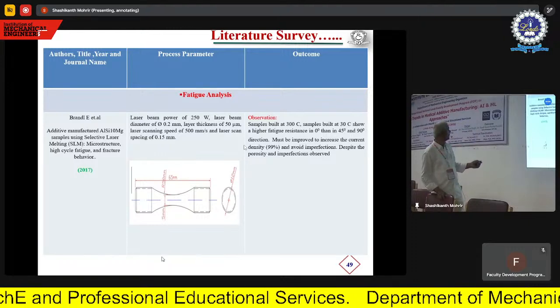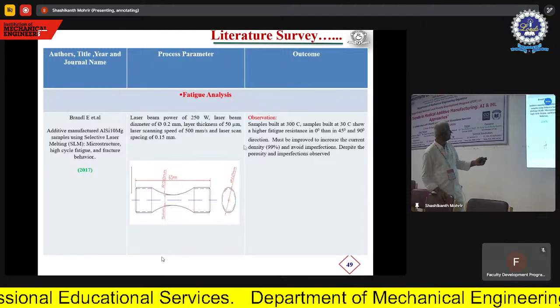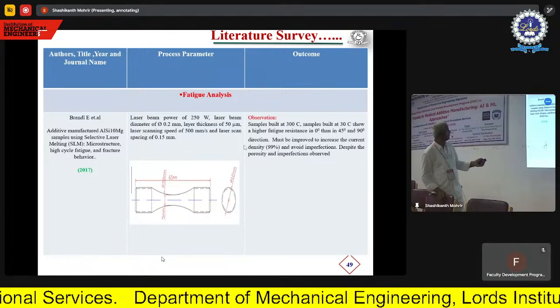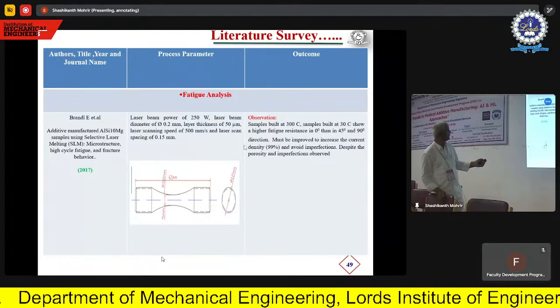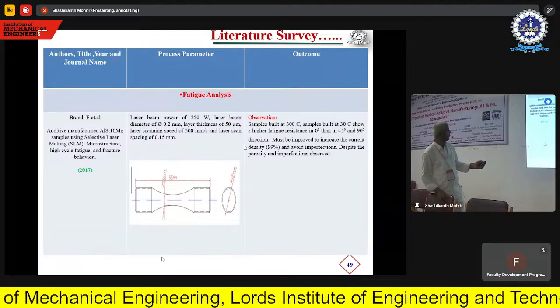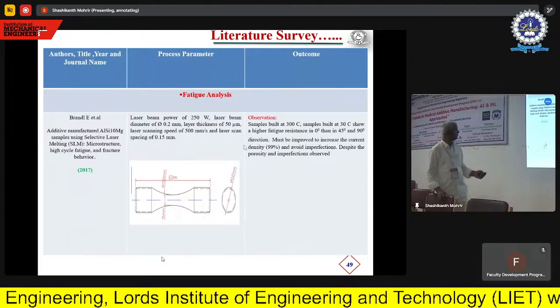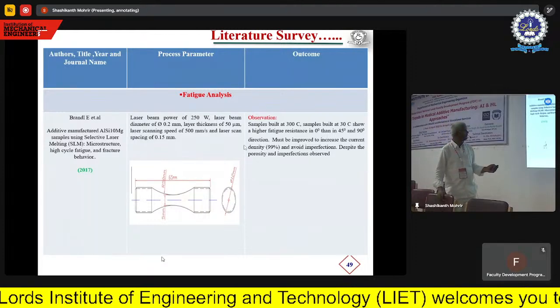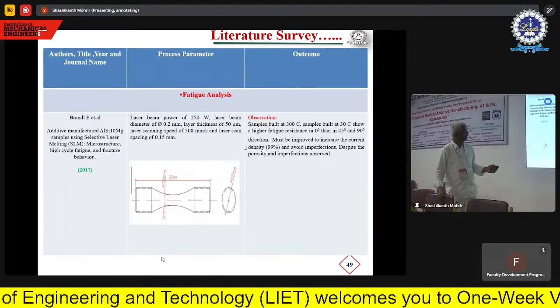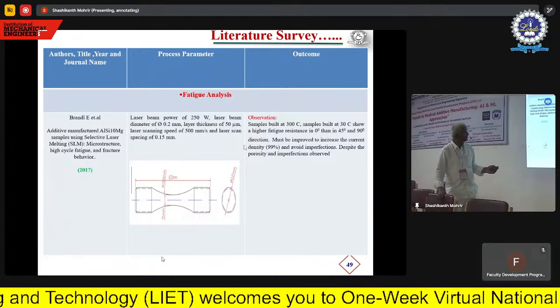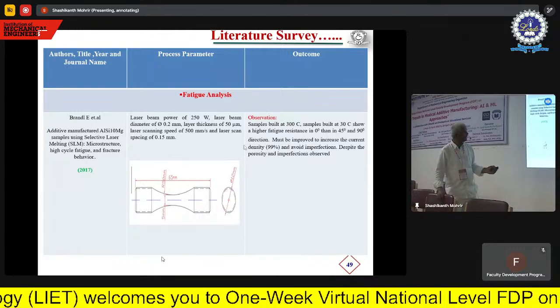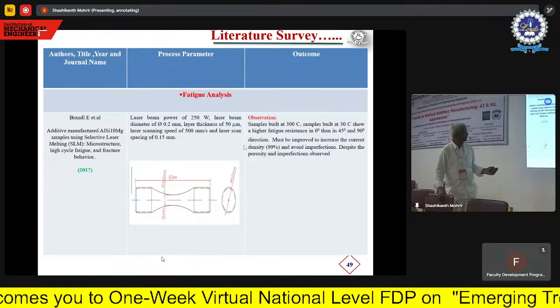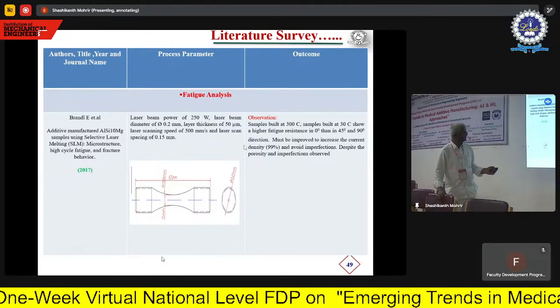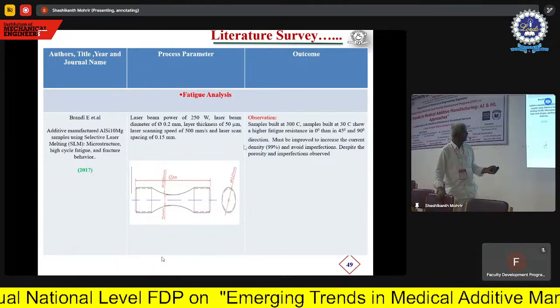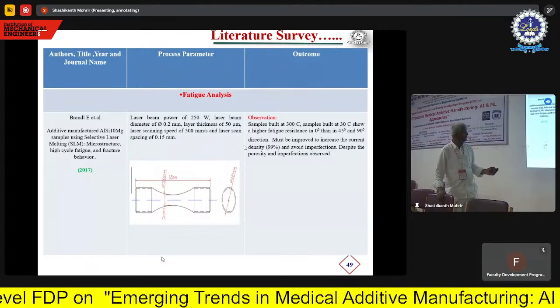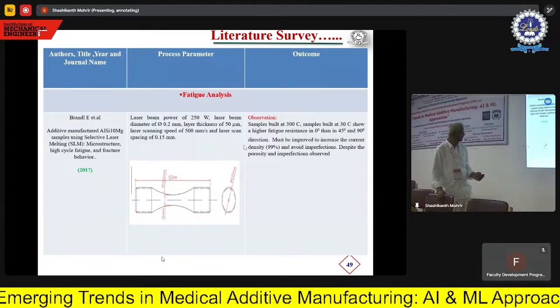So they did the SLM process itself and power, laser beam diameter, layer thickness, laser scan 500 mm per second, and laser spacing 0.15 mm. Observations: samples built at 300 degrees centigrade. Samples built at 30 degrees show higher fatigue strength with the zero orientation than with 45 degrees and 90 degrees. Must be improved to increase density to 99%, avoid imperfection, despite porosity and imperfections observed.